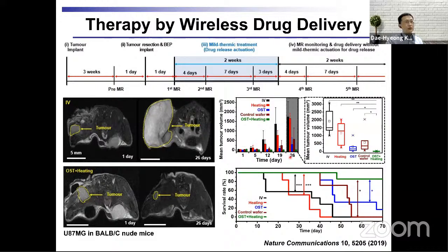And according to the tumor data, after 4-week treatment, the tumor volume could be dramatically suppressed when we use the OST film with the wireless heating. The tumor volume was way smaller than the control groups, and that suppressed tumor volume agreed with the survival rate. We followed the survival rate for about 70 days. And in the experimental group, the survival rate was over 80%, while in control groups, the survival rate was much lower.